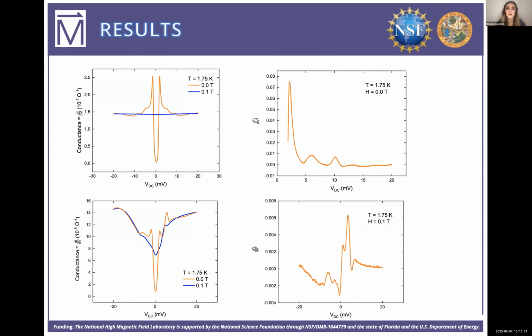So by doing this, we were able to take some really neat measurements and gather some data that's new about samarium hexaboride. Here on the top, both top two graphs are from the aluminum lead samples, which we had expected results for. So by taking these measurements, we were able to know that the tunnel junctions were of good quality. The top left graph is the conductance versus the applied voltage. The orange line shows some features of lead while it's superconducting, and the blue line is when we apply a magnetic field and make the lead behave as a normal metal instead of a superconductor.